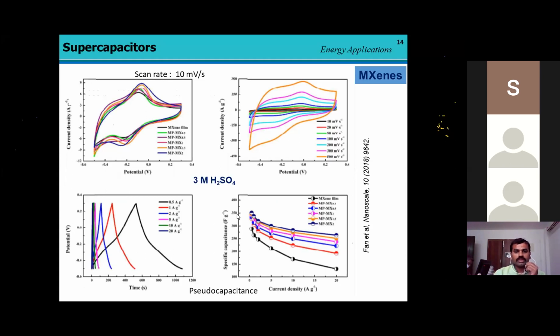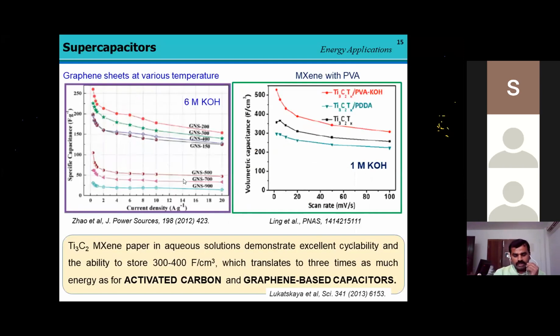They showed the specific capacitance is more than 355 farad per gram with a scan rate of 10 millivolt per second, with 3 molar sulfuric acid as the electrolyte solution. The mechanism mainly follows pseudocapacitance. If we use a neutral electrolyte, then it will form the EDLC mechanism also. Then, for graphene-based materials, a group of people from China developed a graphene material which was compared with the MXene materials also.